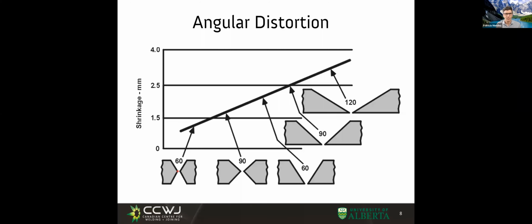Now, when we discussed keyhole electron beam welding or keyhole laser beam welding, that keyhole that goes very deep essentially is like having a very, very narrow joint preparation. It's like having this close to much less than 60 degrees. Now, if I do that close to 0 degrees, then I end up with something that is quite close to zero distortion.